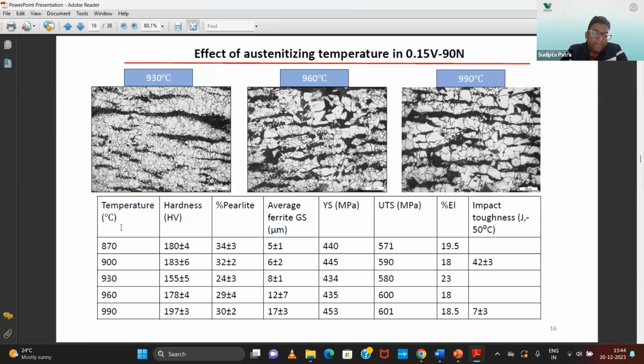And then we have varied the austenitizing temperature also, and we have observed that as we are increasing the austenitizing temperature, due to the precipitation strengthening, our UTS also improves.